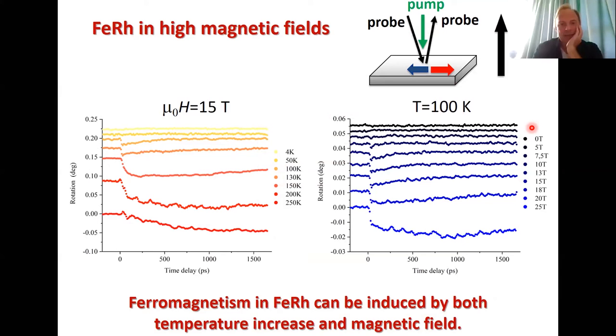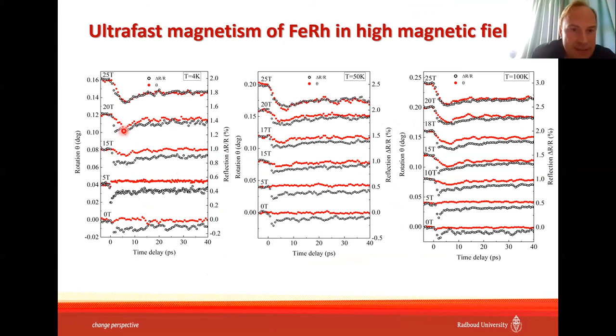And if you now look at the ultrafast time scale, here we show reflectivity with black dots and Kerr rotation with red dots. We first start with low temperature, 4 Kelvin. Reflectivity changes, but it changes fast, so most likely it's a contribution from the electrons, at least it was explained like this. We hardly see any change in the Kerr rotation. Now, there is a very, very small contribution to the reflectivity, which increases slowly. The Kerr rotation appears, and then at the very high fields, 25 Tesla, the Kerr rotation and the reflectivity go in step with one another.